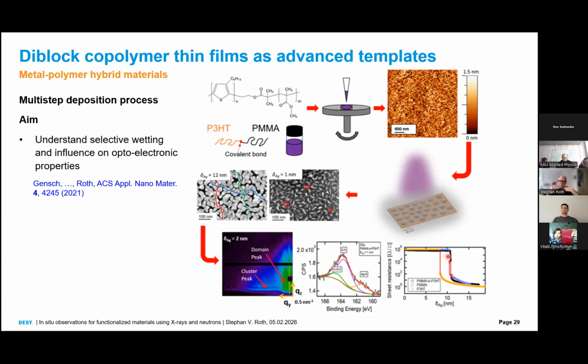However, if you have more complex structures, like multi-layers, or even a diblock copolymer layer where you have lamella like this, and you have one cluster layer and a next cluster layer on top, then I would use BornAgain, because the structure you can put into it is much more complex. And we also use BornAgain. But there's one thing with BornAgain: it's still under development.